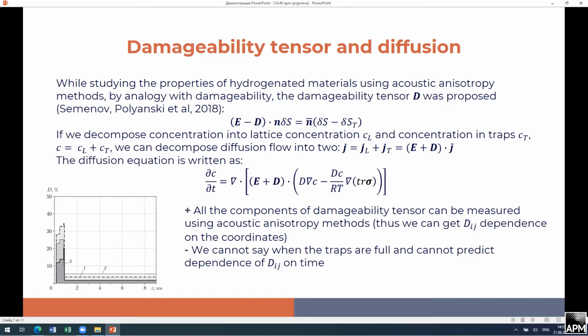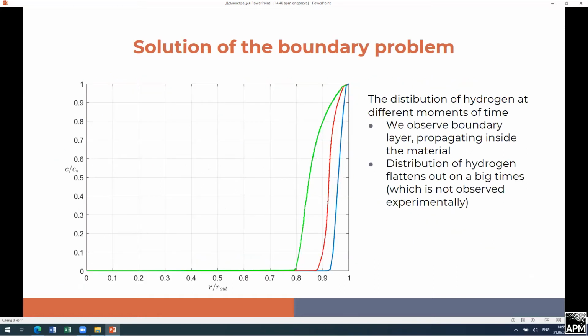So probably this is a way to develop this approach, but for now we just took the measured value of the damageability, which was taken as an analytical dependence, and we solved the mentioned boundary problem with a new diffusion equation.